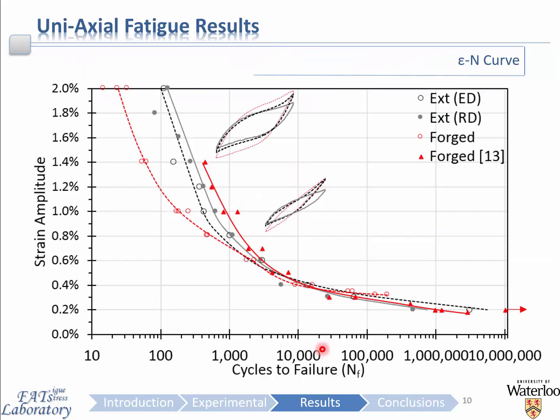Now looking at the uniaxial fatigue results for a variety of different forging conditions, the base extruded material condition is illustrated here, as well as the forged material condition illustrated by the red lines. It is well known that for wrought magnesium alloys, typically they display this asymmetric cyclic response, as can be observed by the hysteresis loops illustrated here and here.